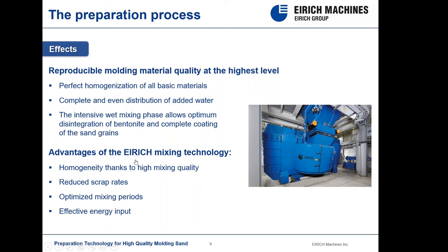And also, once we have the water inside the mixer, we have an intensive wet mixing phase, which can help us due to the speed of the rotor that can be increased. That helps us to move the water and the bentonite together. So the activation of the bentonite and distribution of the bentonite around the sand grains is more even, and it's better.